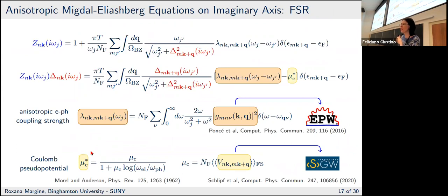There is a study coming from Sangeeta's group, I don't remember the name, where they estimated mu star for between 10 and 20 materials, and they found that in most of them, the mu star falls between 0.1 and 0.2, roughly 0.15. So I would say that probably for a lot of systems, an average mu star of 0.15 gives reasonable results.